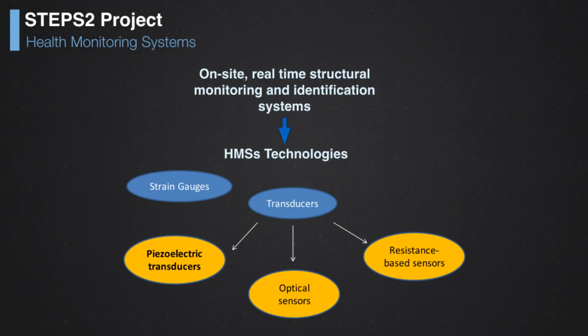There are certain drawbacks of this approach, of course, because the fiber is extremely sensitive to temperature variation. It's also brittle. You cannot apply easily this kind of optical sensors in space. And then there are the resistance-based sensors, of course, the same approach of the piezo-resistive or piezo-impeditive materials. And you have to cope with all the problems related to the space environment, of course. So micrometeorites, atomic oxygen, ionic bombardment, and huge temperature variations.